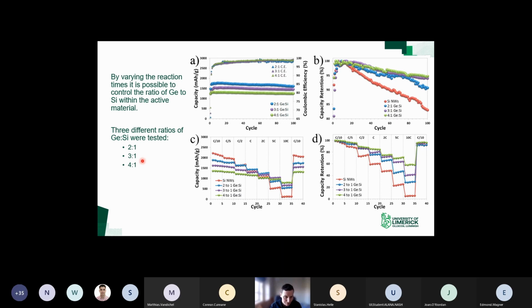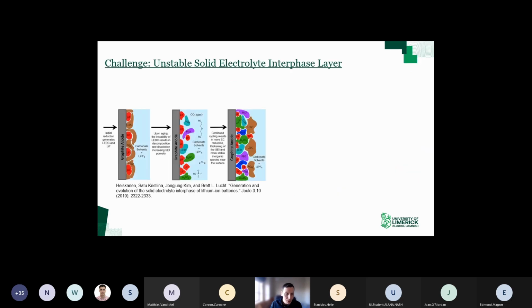Well, then you want the high silicon content there, because that will give you the high capacity. If you want something that has high power capability, maybe like a power tool, well then maybe you want to move towards more germanium. For all cases, we saw that the germanium silicon heterostructure behaved better than silicon on its own. Okay, and again, I guess that's what we expected. So that was the initial studies we had on these materials.